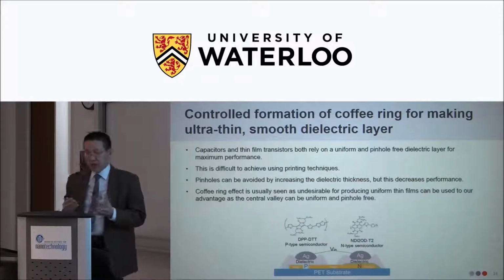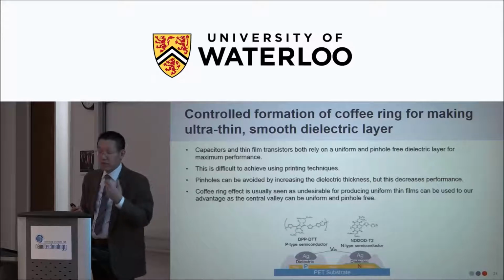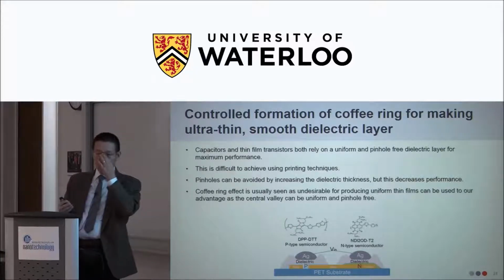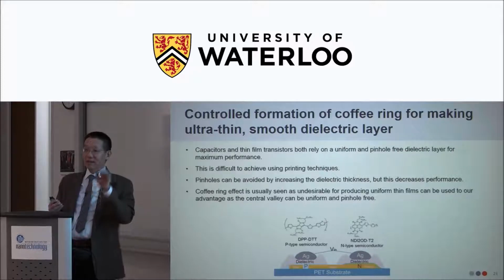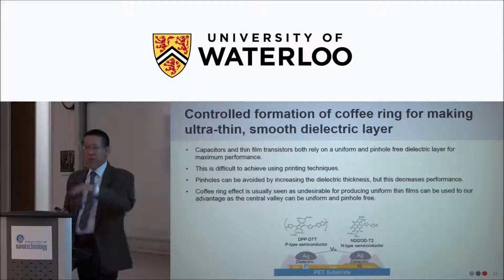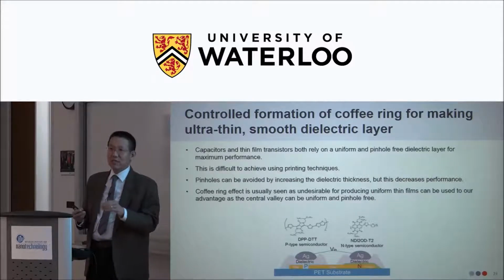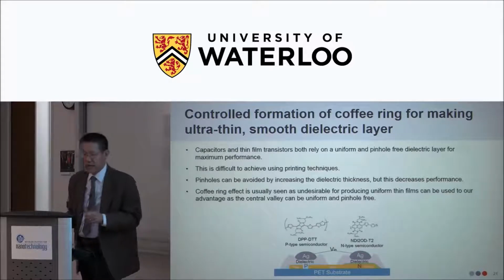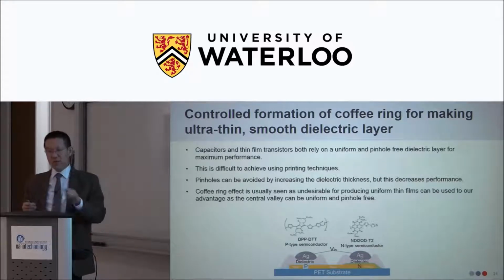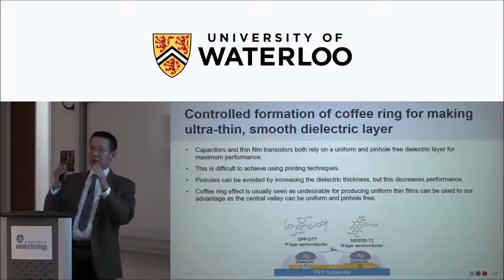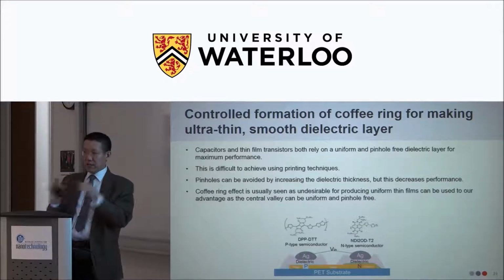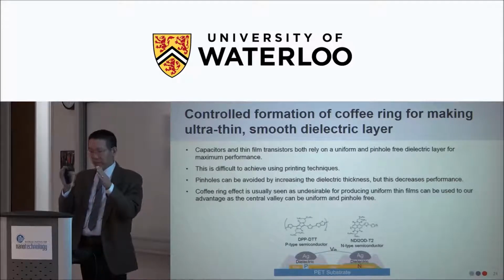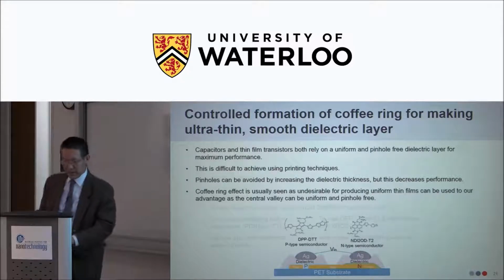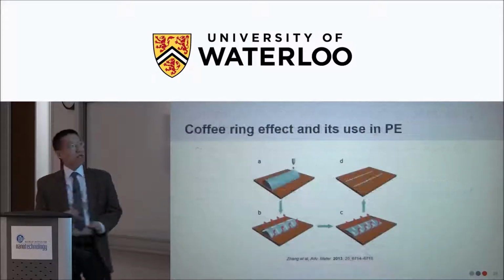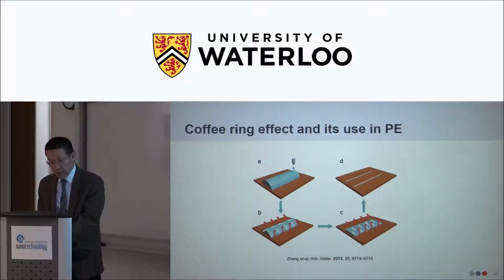And so what we did here, we faced a problem: when you print transistors, you want a very thin dielectric layer, very dense, pinhole free, so you can have low voltage operation for your transistor. But when you print dielectrics, it's not easy to get a thin, pinhole-free layer, right? So what we did here, we used the coffee ring effect. We print a dielectric layer and control the drying process, because the coffee ring process gives a very flat layer.